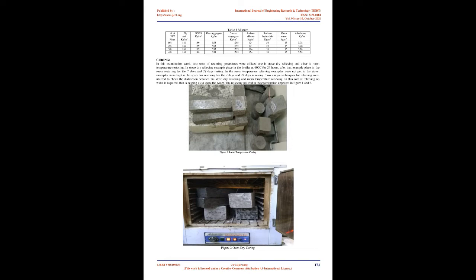Olivia and Nikraz, 2011, analyzed the water permeability of geopolymer concrete made with fly ash, with water to geopolymer ratio of 0.36-0.46, subjected to oven curing at 60 degrees Celsius temperature for 24 hours. They found that geopolymer concrete showed lower water permeability values, 2.45-4.65 x 10^-11 m/s, than the standard concrete because of its denser mix and small inter-pore connection. They also stated that the most significant parameter influencing the properties of geopolymer concrete was its water to geopolymer ratio.